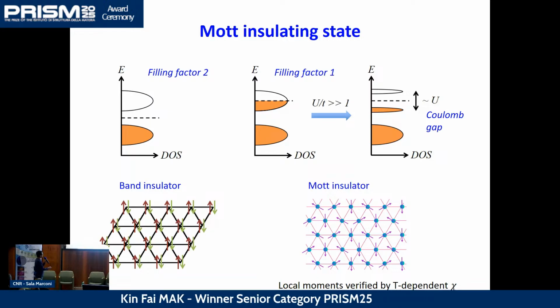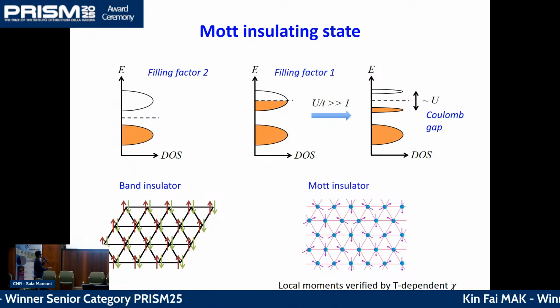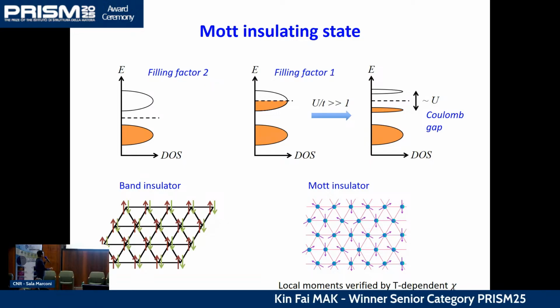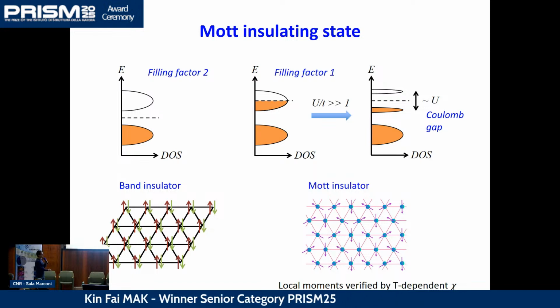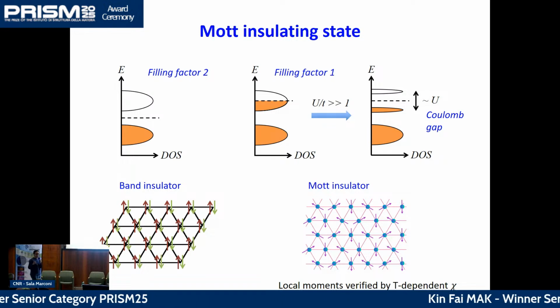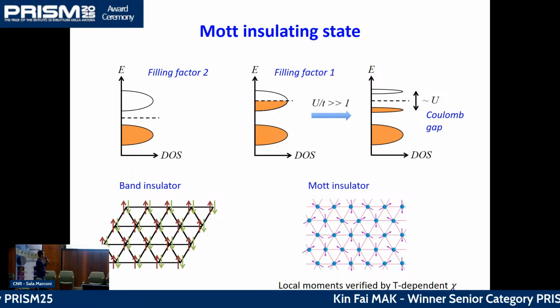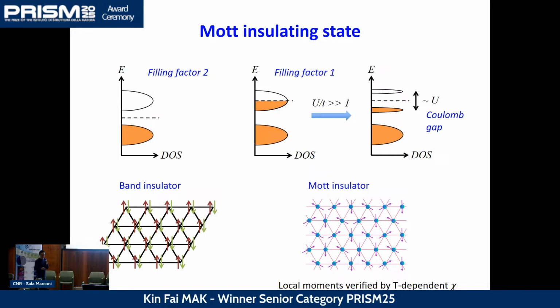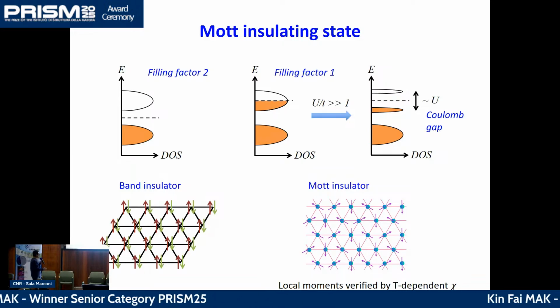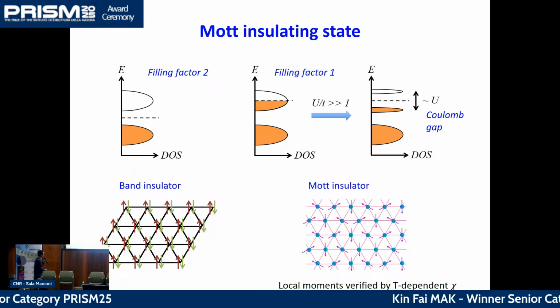But of course, we are in this limit here. The U over T is very, very large, and that will automatically open up a Coulomb gap in the system to save some energy. Basically, what's happening is that the electrons, rather than moving around, are totally localized due to the Coulomb repulsion with each other. And that's the lowest energy configuration for the electrons. If they move around, you cost more Coulomb energy, and that's not energetically favorable. And we also verified that local moments indeed emerge, but I will skip that part.